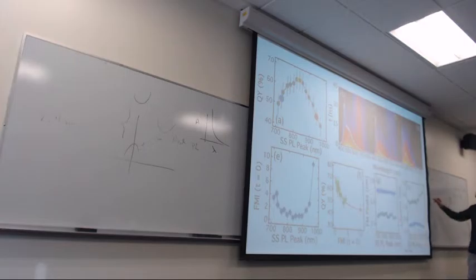What you're going to see then is a really fast decay. You actually see multiple decays before you get to the microsecond slow decay. This dominates the area under this curve. This is a log scale. So this emission, because it's so fast, makes no contribution to the steady-state PL.